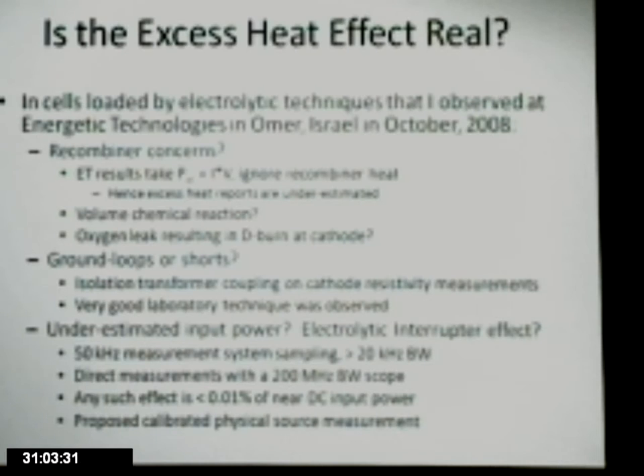How about ground loops or shorts? Isolation transformers were used throughout for the resistivity measurements of the palladium cathode, which is used to gauge its loading. And again, very good laboratory technique was observed. I didn't see any really shoddy laboratory practice from what you would expect to see in a laboratory doing careful measurements.